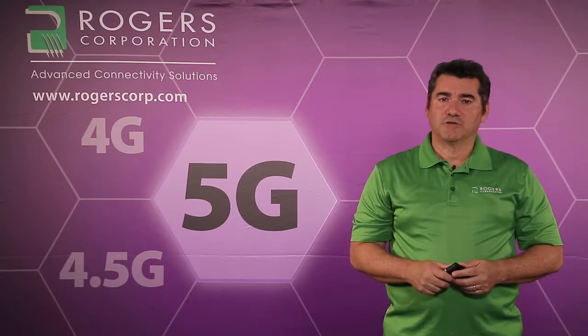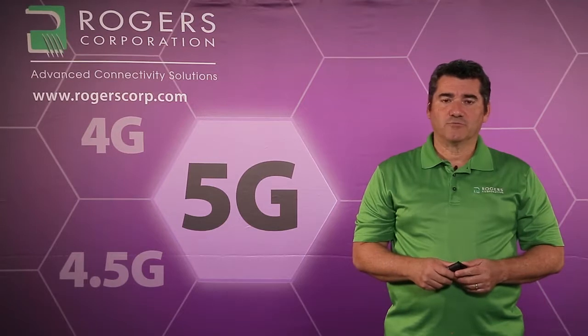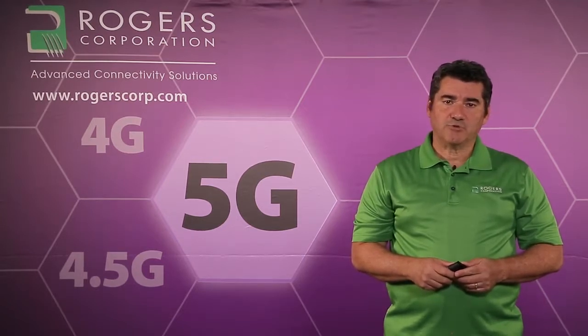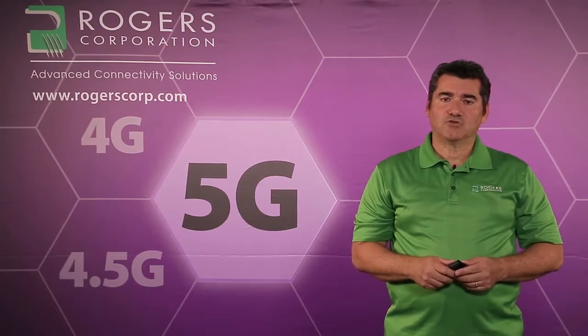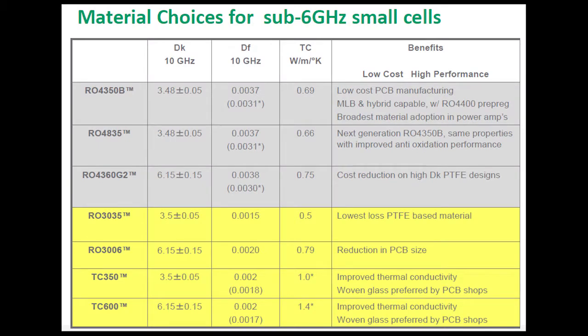High-performance materials can be divided into 2 subsets. We have thermoset materials that focus more on cost, while we have PTFE materials that focus more on performance. Which material to use depends on the application and the goals of the designer as to what kind of performance and cost value they need to achieve. Our RO4000 family of products consists of thermoset ceramic-filled woven glass materials that have loss in the area of .003 to high .003s depending on 2.5 or 10 gigahertz, and dielectric constants of 3.5 to 6.15. In combination with the RO4000 prepregs, these materials offer a very cost-effective manner in which to build multi-layer boards. These products are most used in wireless infrastructure base station power amplifiers.